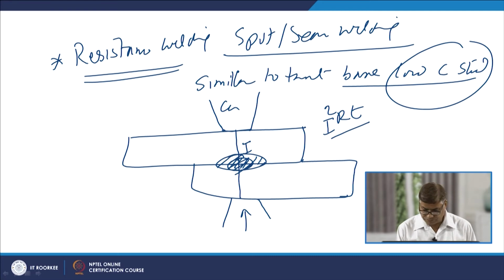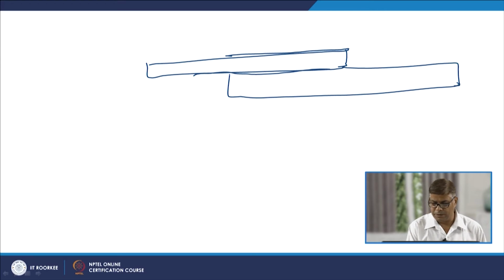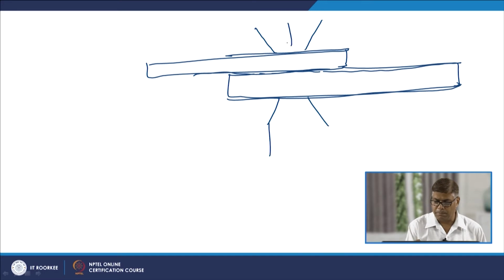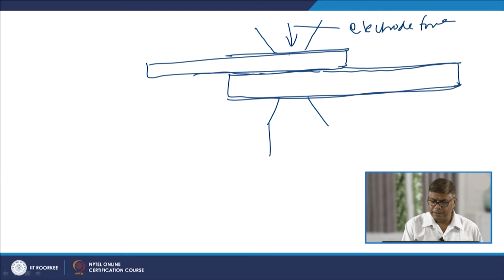Now, coming to the aluminized steels, in these cases the aluminum coating is there on both sides. So, say this is the sheet coated with a thin layer of aluminum on both sides, and likewise there is another sheet which is also coated with aluminum. So, this thin layer of aluminum will be there at the interface, and both sides will have the electrodes which will be used to apply the electrode force. Then the current will be allowed to flow across the sheets to be joined, and that will generate the heat through the I square R T principle.